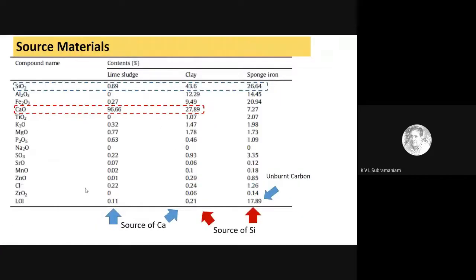Now, before we start making cement, we first have to understand the raw materials and look at what each of these materials is bringing in as a source. So if I look at lime sludge, look at these three columns. The oxides of these three are given in the first column. If you look at SiO2, which is the silica, clay is rich in silica. It has 43.6% silica, and sponge iron also contains silica. So basically, I can use these as my sources of silica.